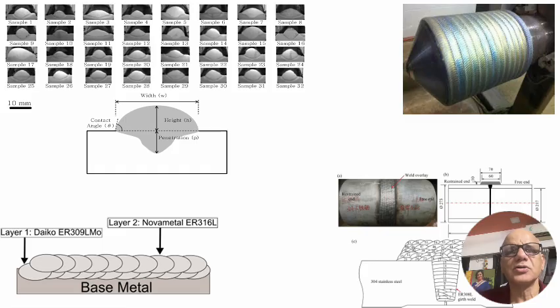So thank you for listening to this video on overlay, buttering, hard facing, and different entities which are required to be done and achieved. What we actually get is a dye penetration test to see that there are no surface defects allowed, because any surface defect means crevice corrosion is going to increase. Hard facing will have a crack initiating from there, built up. If it is there, it is not going to be sound metal for us to have a build up. If it is for lamellar tear, then that could be a potential point acting as a notch. So a lot of care is required when we are going to do this build up.